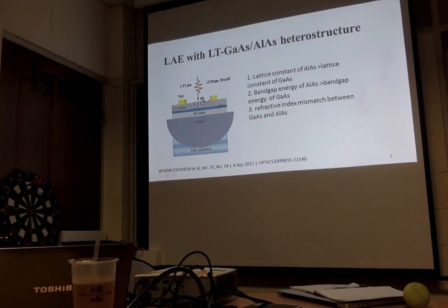And if we are using the MBE tool, it will be very hard for this tool to grow a layer thicker than 1 micrometer. And 1 micrometer is very thin, and if you really hold it, it will break, I mean, by human hand. So it will be better to have a thicker, stronger substrate to support it. So that's why we use SI gallium arsenide as the substrate and grow LT gallium arsenide on it. Okay.